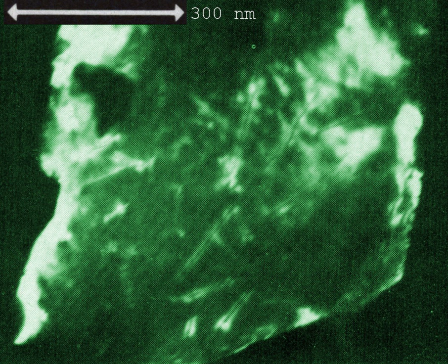Ion tracks are damage trails created by swift heavy ions penetrating through solids, which may be sufficiently contiguous for chemical etching in a variety of crystalline, glassy, and/or polymeric solids. They are associated with cylindrical damage regions several nanometers in diameter and can be studied by Rutherford backscattering spectrometry (RBS), transmission electron microscopy (TEM), small angle neutron scattering (SANS), small angle X-ray scattering (SAXS), or gas permeation.